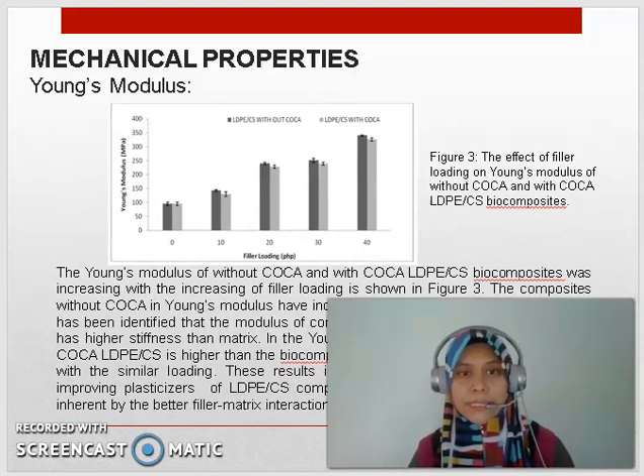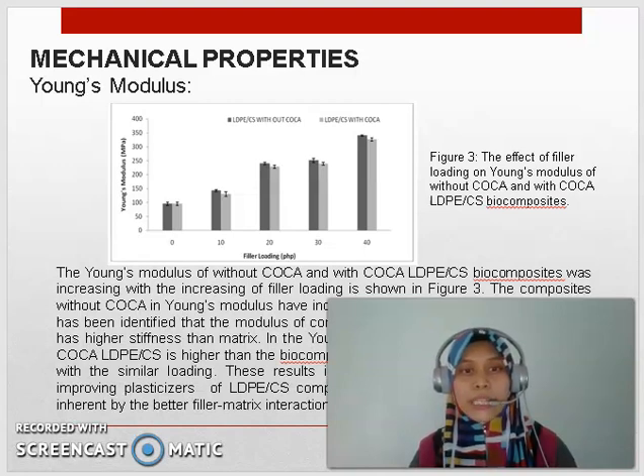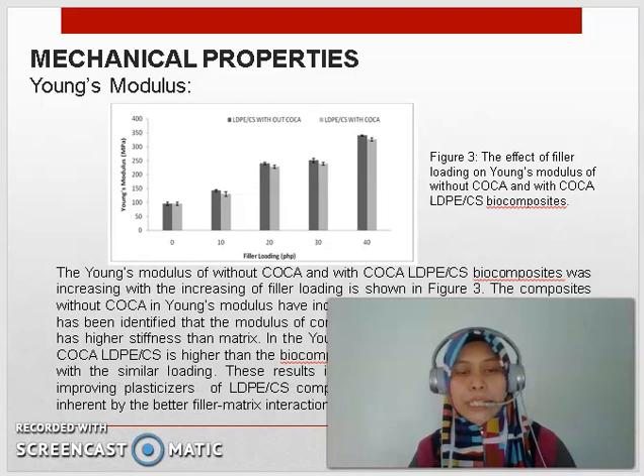For the Young's modulus, the Young's modulus for without COCA and with COCA for LDPE or CS biocomposites was increasing with the increasing of filler loading, as shown in Figure 3. The composites without COCA in Young's modulus have increased when filler loading is increased. It has been identified that the modulus of composites can be increased when the filler has higher stiffness than the matrix. The Young's modulus of biocomposites without COCA for LDPE or CS is higher than the biocomposites with COCA, even with similar loading. The results indicate the efficiency of COCA in improving the plasticizer effect of LDPE or CS composites, while the polymer chain mobility is enhanced by the better filler matrix interaction.